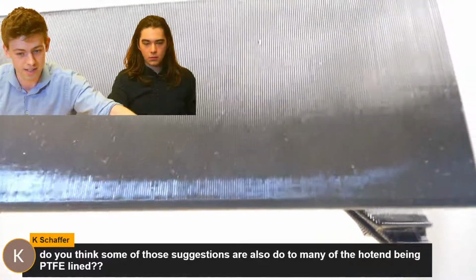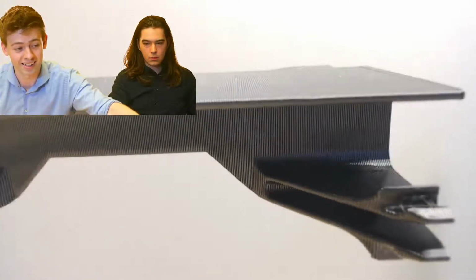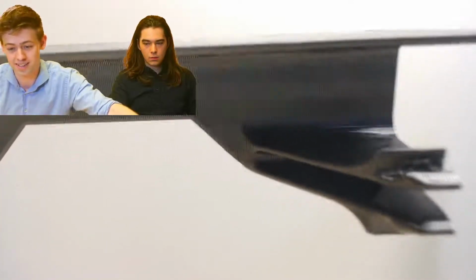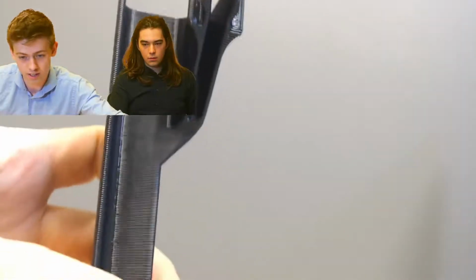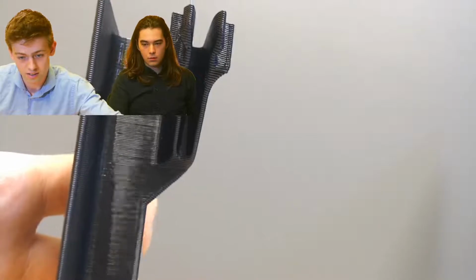So this is 260 degrees. It does look very nice, but having this good a surface quality at 260 degrees with PLA is not something you would expect to see. And look at these, these are overhangs, by the way. The part prints like this. These are all overhangs, and they're looking very good, I have to say.